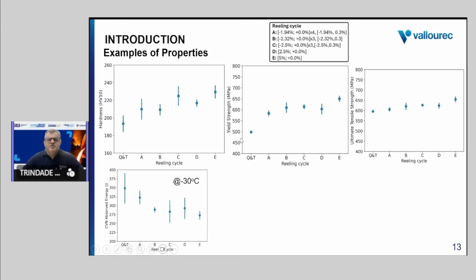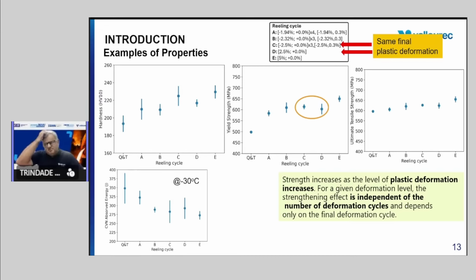This happens for hardness and also for the strength. You can see the YS increasing, and the UTS as well, and the toughness, measured by absorbed impact energy, decreases considerably after aging of those materials. What is quite interesting to observe, and I will not demonstrate it here but you have to believe me, is that D and E are not cyclic, they are just strained by monotonic force, like a single tensile test, and A, B, C are cycles, with different numbers of cycles.